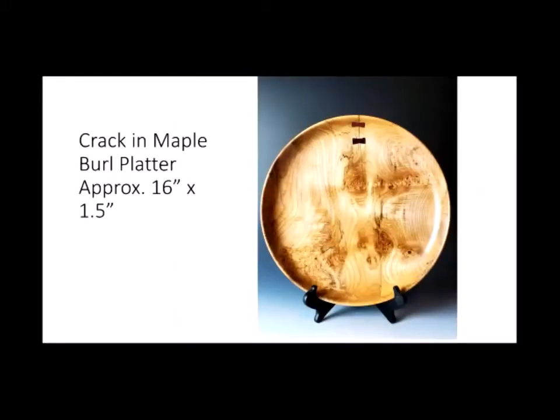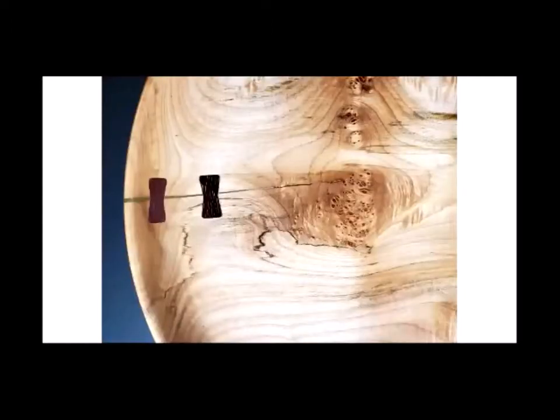Here's another piece. There was a crack in this that happened after I turned it and finished turning it and it dried. It was already dry, but it was turned very thin just because it was a thin piece to start with. This crack developed after it was finished. It was probably 3/16 of an inch thick at that point. I didn't want to lose the piece. You could have probably used CA glue in here, but I used epoxy